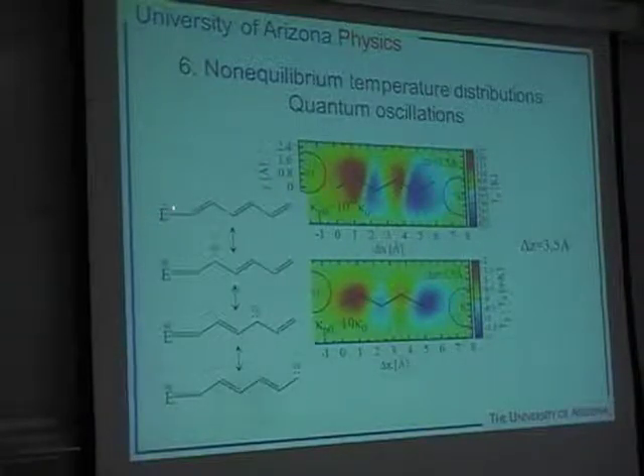And so you see, if this is the hot electrode, it can put its electrons here, here, or here, i.e. there, or there, or there. And so one thing which doesn't quite come out of this picture is that the proximal orbitals, so this orbital is proximal to the cold electrode, it ends up that the proximity effect is also relevant. So basically the hot electrode can put its electron there, but so can the cold electrode, so you basically get an intermediate temperature. But all the rest of the temperature oscillation you can understand from these kind of diagrams.